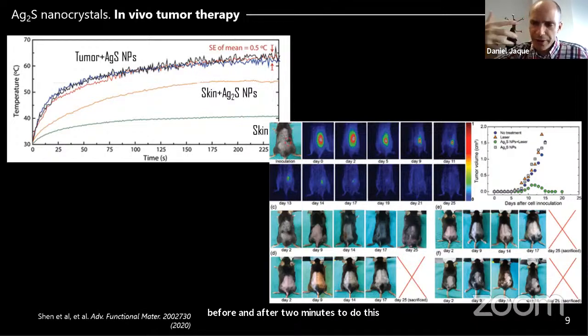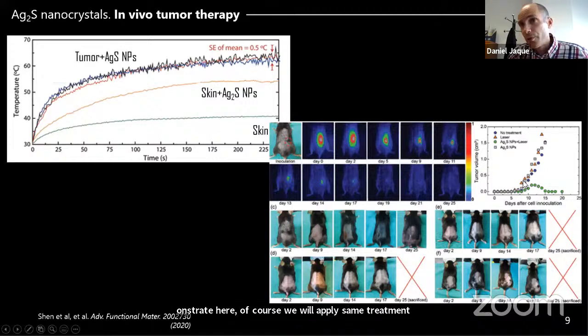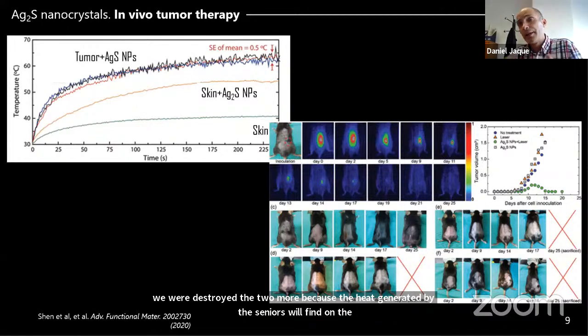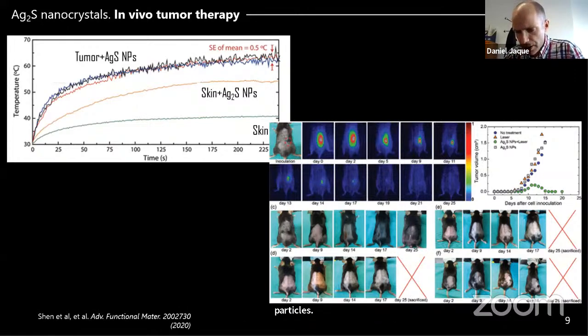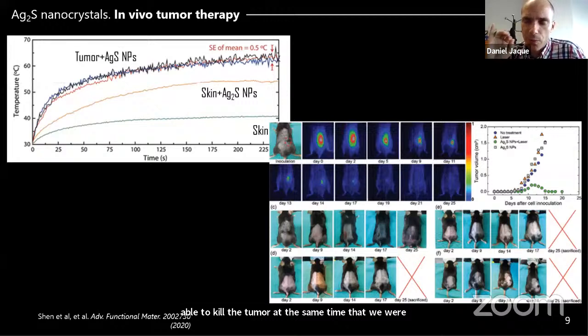So what we demonstrate here, of course, if we apply the same treatment without silver sulfide nanoparticles or without laser, we observe that the tumor volume is continuously growing, and after 15 days the animal is dead. So with treatment with silver sulfide nanoparticles, we were able to destroy the tumor because of the heat generated by the nanoparticles, at the same time that we were measuring the tumor in a very precise way.